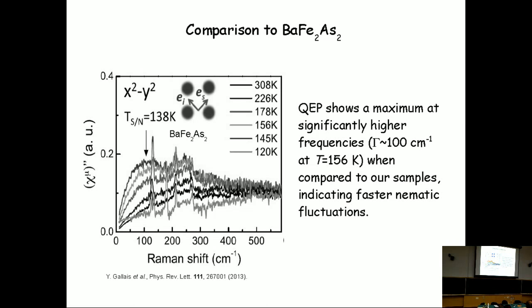Because the system has more than the spin degree of freedom, right? This is why you want to treat nematicity as a separate order parameter, because there is this orbital freedom. Yes. And actually, we were one of the first to point out this is a ferro-orbital order, which is why you can see it with Raman, in the momentum equal to 0 limit, right? So it makes sense that there is an onset. It's not too surprising, I think. What's really important is to see whether these two onsets are separable. At the moment, it seems that they are too close.